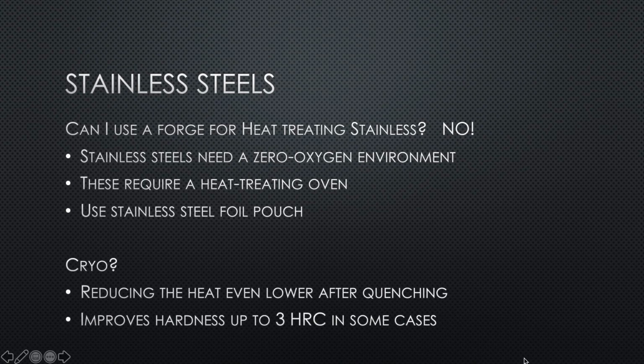So let's talk about stainless steels. Also a question I see all the time: can I use a forge for stainless steel? No, you cannot. They really need a zero oxygen environment. You really need a heat treating oven, because you need to put the blade in stainless steel foil, and that gives it a zero oxygen environment.